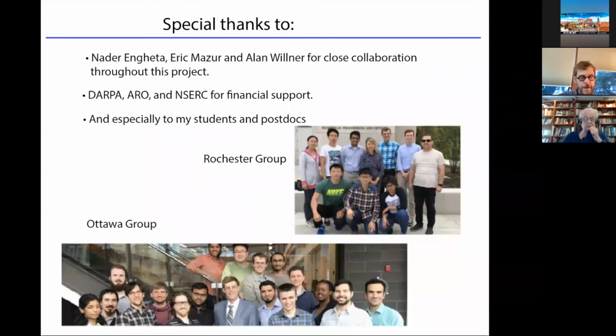You want epsilon and mu both to go to 0, but not necessarily at the same rate. That's the first comment. Second comment is that in reality, any material that we've studied so far, I mean the entire community, the imaginary part of epsilon is large enough that this effect does not show up in the laboratory. It's a conceptual point that we were working on, at least at this stage.